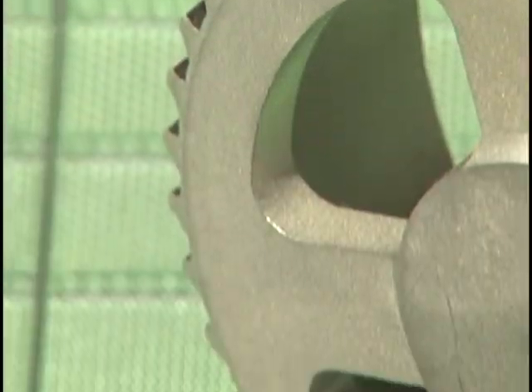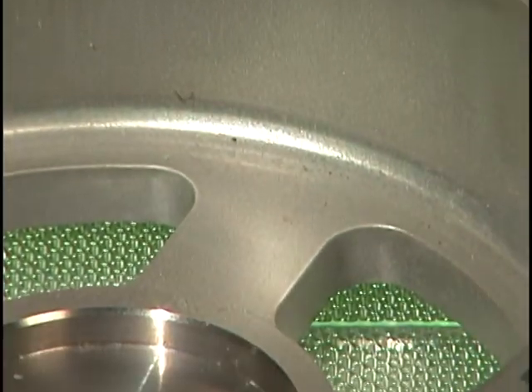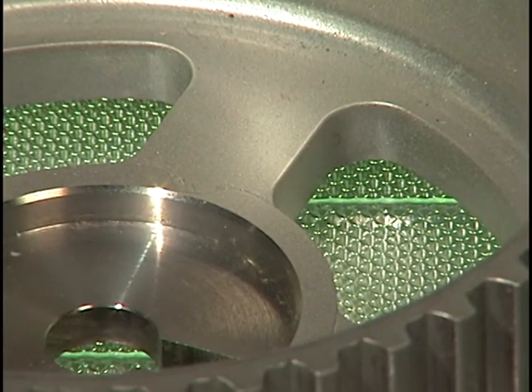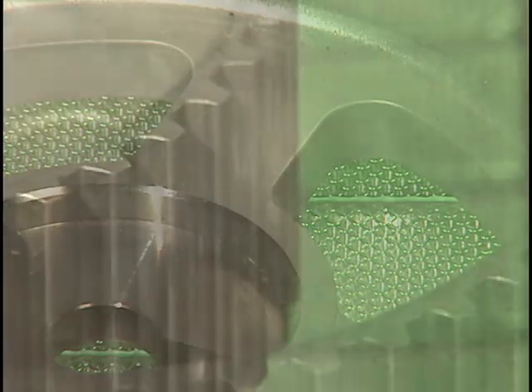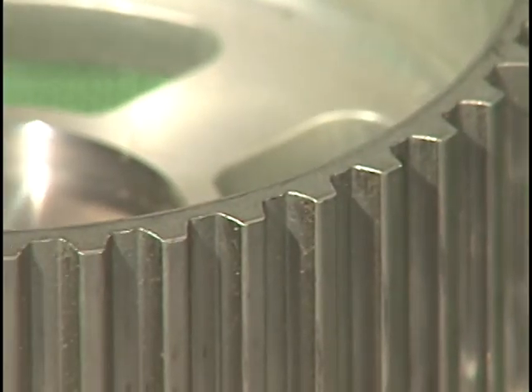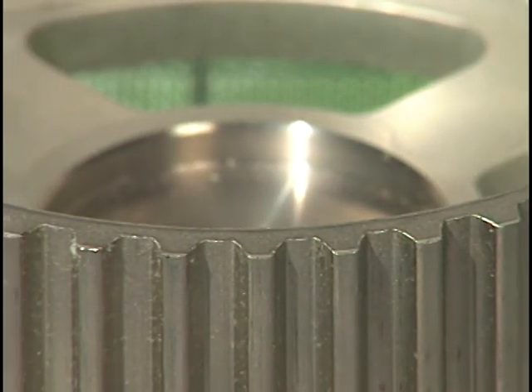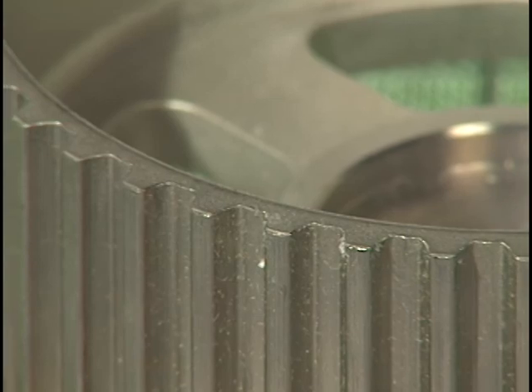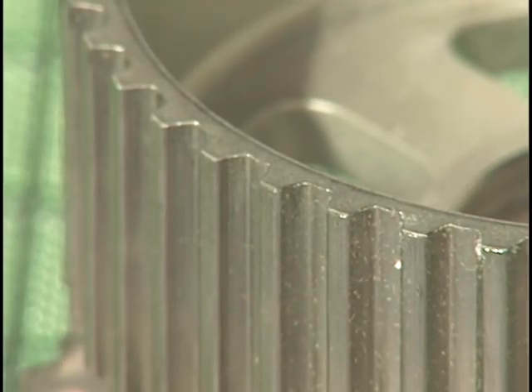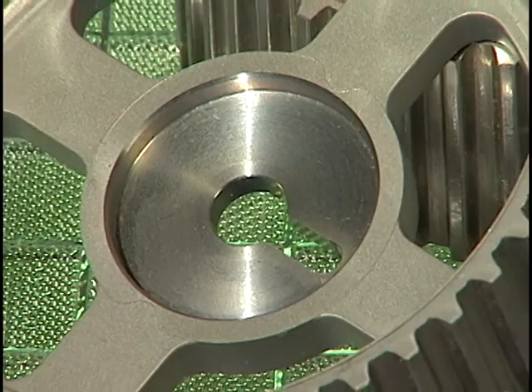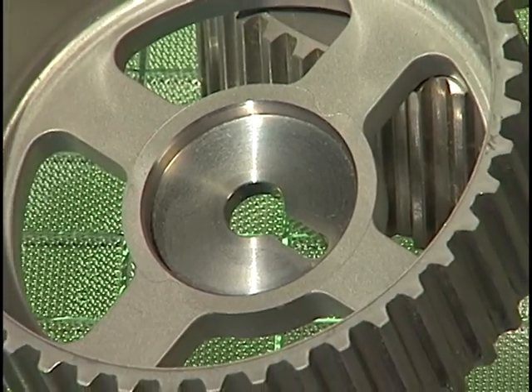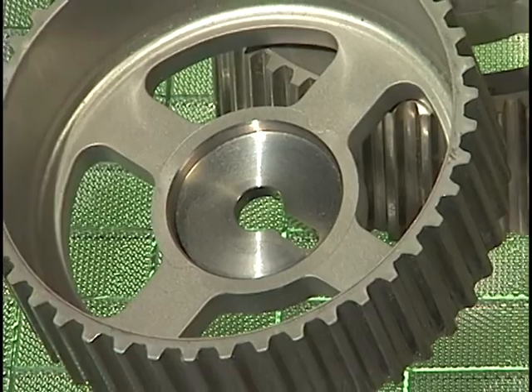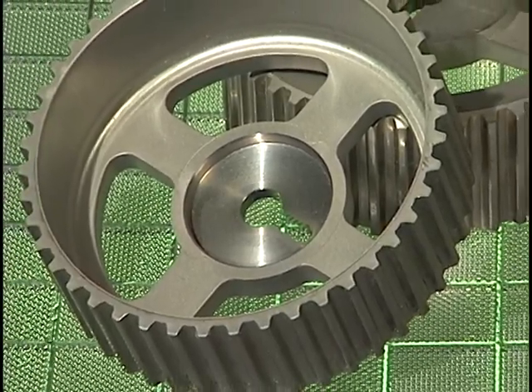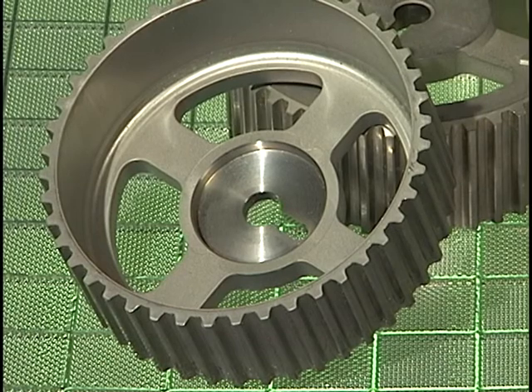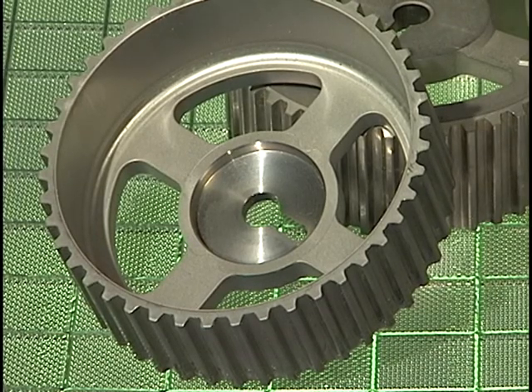It is made to a density of 6.7 grams per cubic centimeter and has a tensile strength of 49,300 psi and a yield strength of 21,750 psi. Successfully producing the large pulley required a special powder mixing technique of first coating the particles with a liquid binder, followed by the addition of a substantial amount of a special lubricant. These additives were completely removed by precisely controlled vacuum dewaxing. Machining the inner diameter counterbore is the only secondary operation.